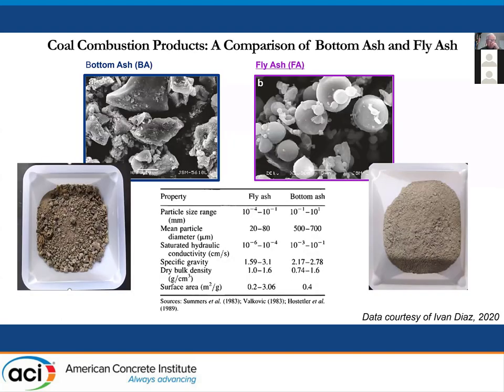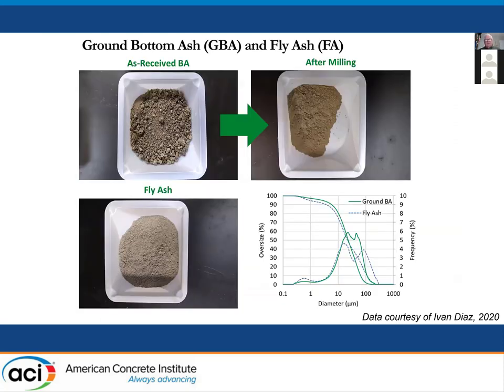There's a micrograph on the left, and you see the sample is more like sand, very fine sand size, whereas the fly ash on the right isn't. So you see the big difference in particle size of the raw ash, about a factor of 10 larger in the bottom ash mean particle diameter. But we can mill that ash.